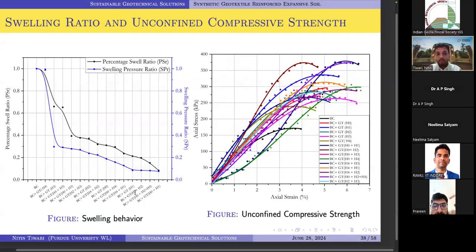If you place it at the top, and either at 1/3 or at the half, it will work out really well. Even if you place it at the bottom, I feel the values are almost the same, so not much difference. But only your drainage will improve, so you'll have a low swell percentage. For the swelling pressure, it will be almost the same. So not really this one, but if you go to these 3, 4, they really perform well.